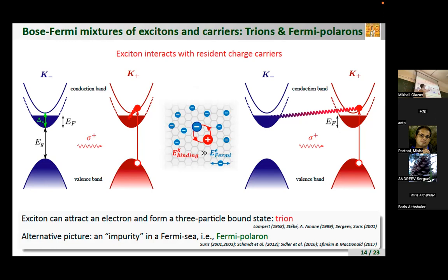Here, the exciton binding energy is huge, hundreds of milli-electron volts. The trion binding energy is also large, 20 milli-electron volts, and the scale of disorder is something like 1 milli-electron volt. So you can easily tune here, you can easily study the physics of trions, you can easily study effects that may not be related only to the formation of these bound localized three-particle complexes.